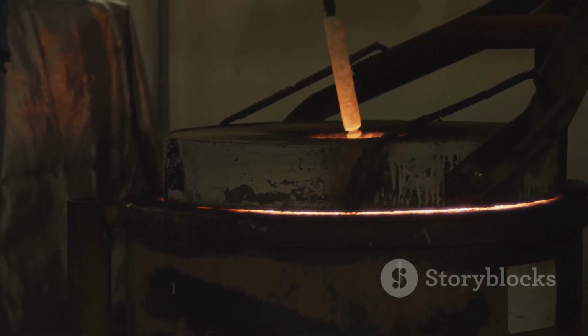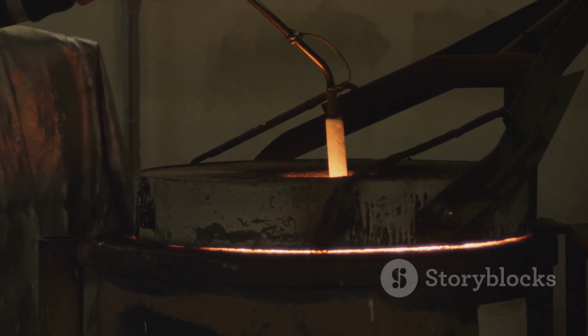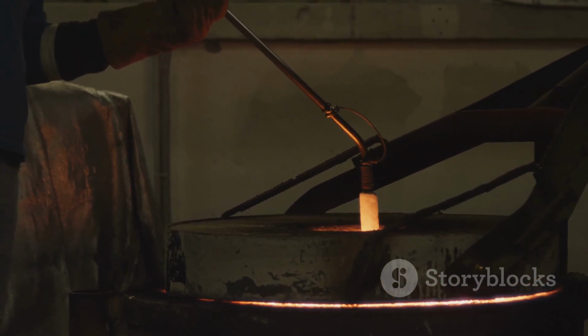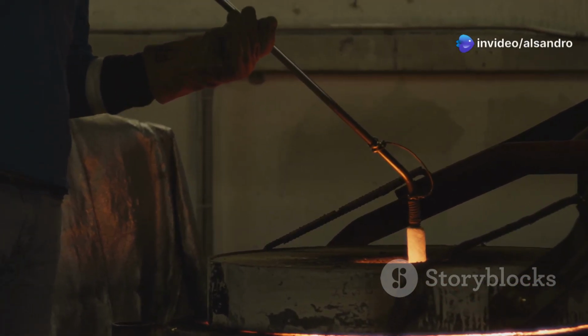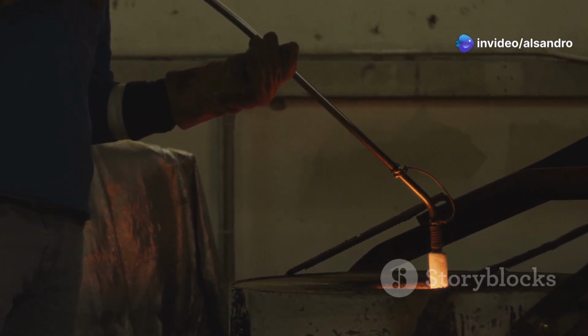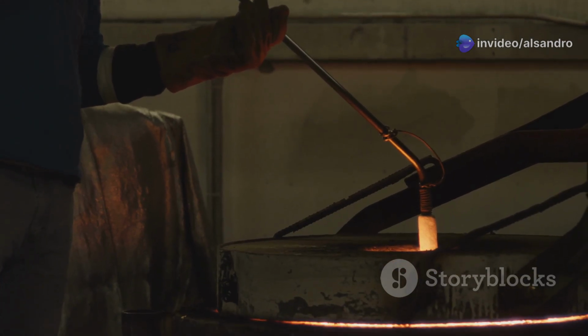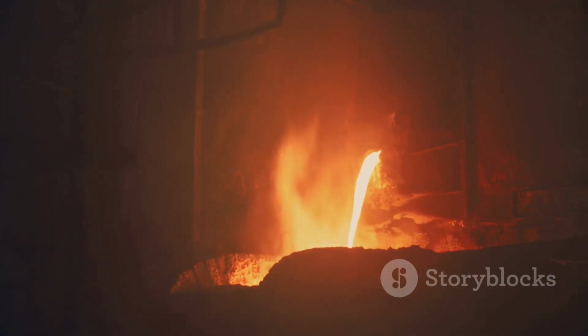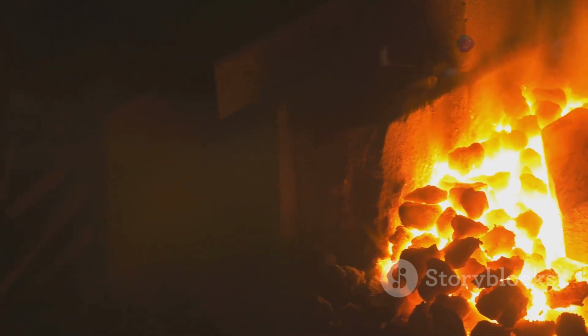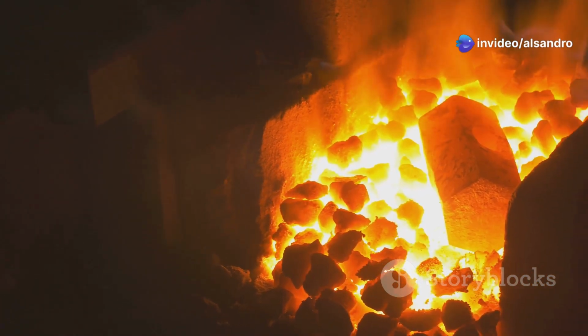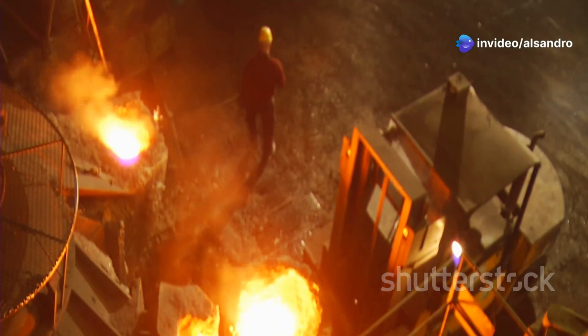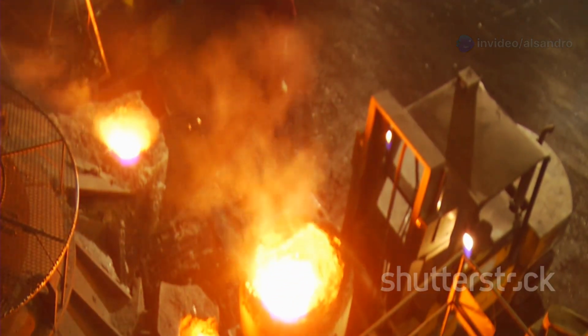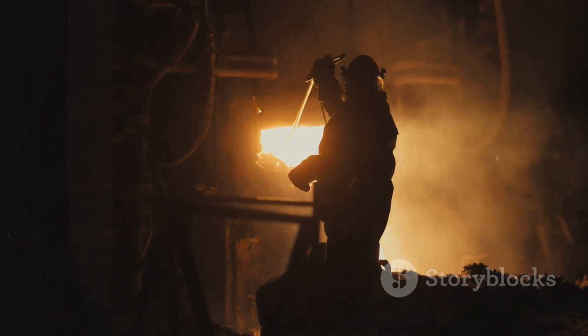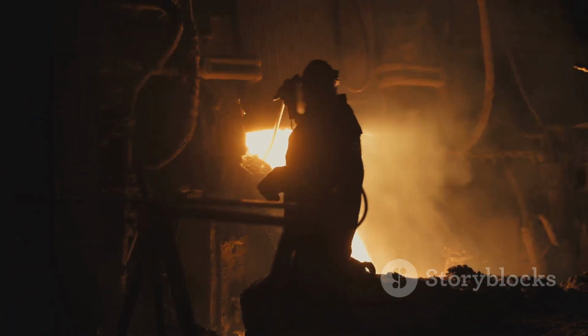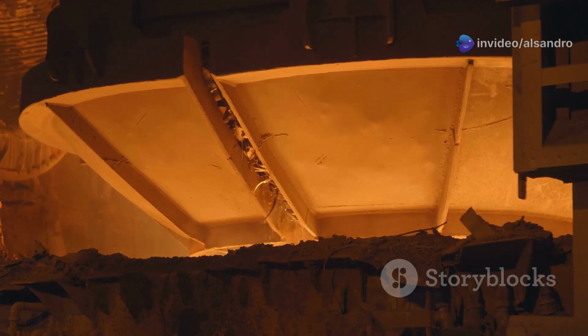Temperature also plays a starring role in this drama. If your furnace is running at too low a temperature, the slag becomes thick and viscous. This sticky, slow-moving slag is much more likely to cling to the furnace walls instead of floating freely where it can be removed. On the flip side, running at too high a temperature can cause its own set of problems, like burning off valuable alloys and creating even more oxides. Finding that Goldilocks temperature, not too high, not too low, is critical. It requires careful control and monitoring, because even small variations can make a big difference.